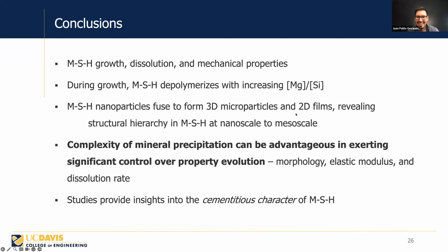That's fantastic. Moving on to another question here from Yi Xian. Thank you for the talk. What is the reason behind selecting mica as the substrate for growing MSH? Mica is very inert, so it's highly unreactive with water. Especially for our dissolution experiments, that's very valuable because it dissolves several orders of magnitude lower than MSH. That means that when we do our experiments, we can use it as a reference substrate, knowing the height of mica is not changing, and we can align all of our images in the Z direction, the height direction, so that we can get absolute heights for the precipitate.